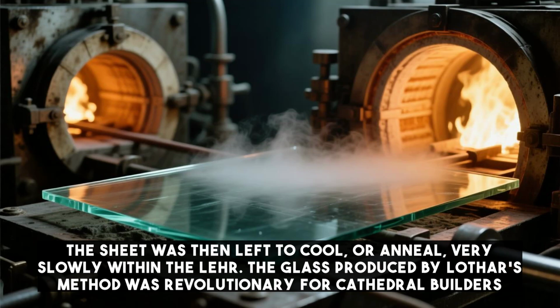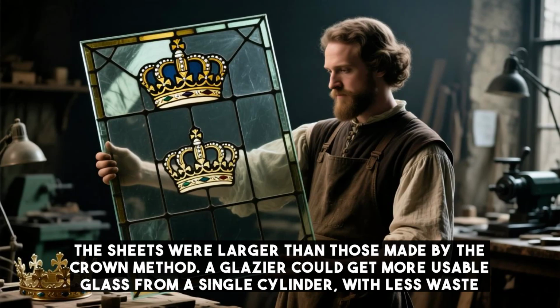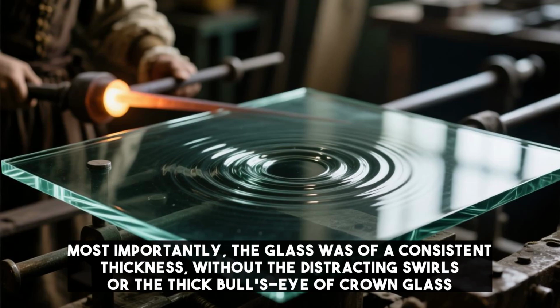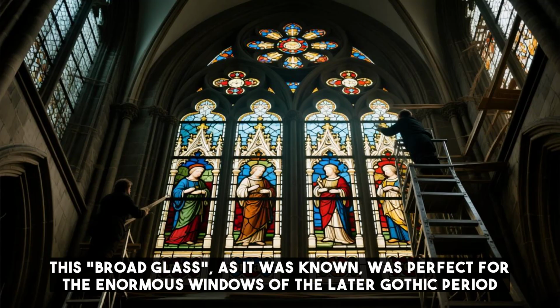The glass produced by Lothar's method was revolutionary for cathedral builders. The sheets were larger than those made by the crown method. A glazier could get more usable glass from a single cylinder with less waste. Most importantly, the glass was of a consistent thickness, without the distracting swirls or the thick bull's eye of crown glass. This broad glass, as it was known, was perfect for the enormous windows of the later Gothic period.